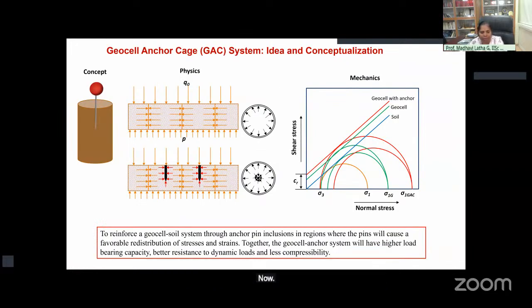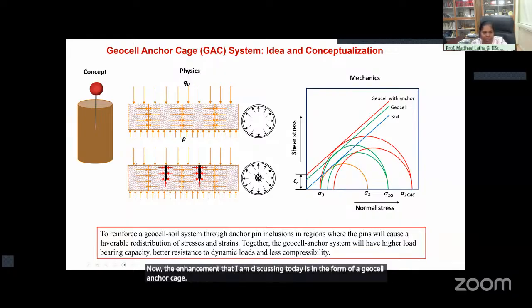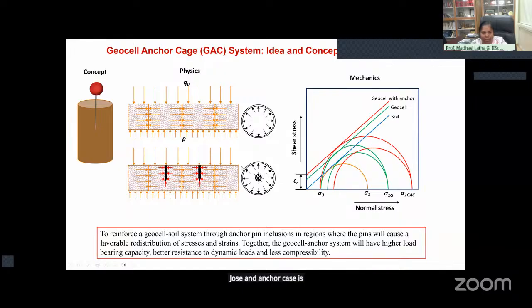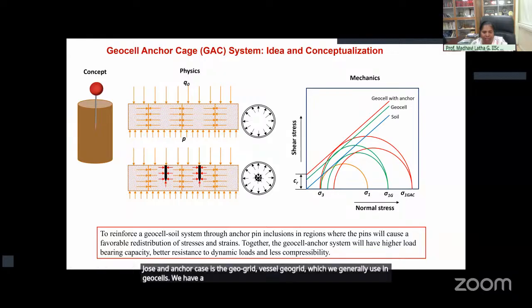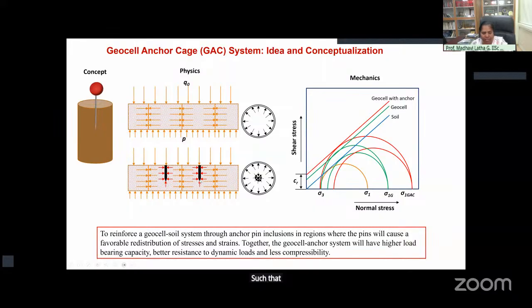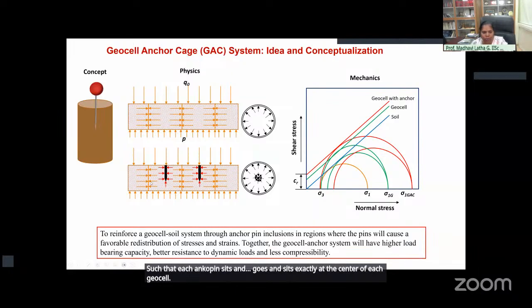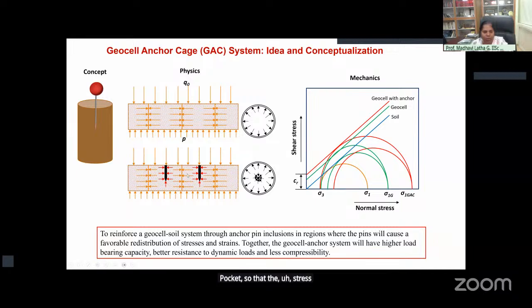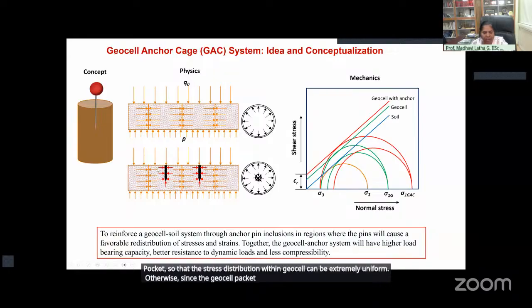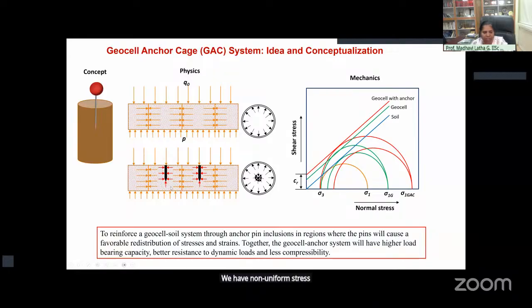Now, the enhancement that I am discussing today is in the form of a geocell anchor cage. A geocell anchor cage is the geogrid, the basal geogrid, which we generally use in geocells. We have a basal geogrid, and to the geogrid we provide anchor pins such that each anchor pin sits exactly at the center of each geocell pocket, so that the stress distribution within the geocell can be extremely uniform. Otherwise, since the geocell pocket size is large, we have non-uniform stress distribution within geocell pockets.